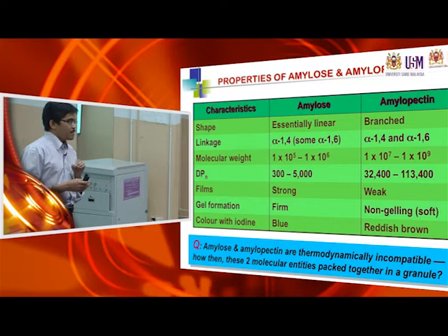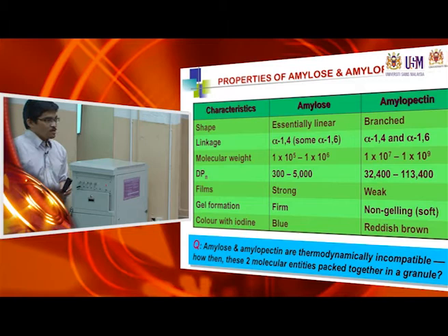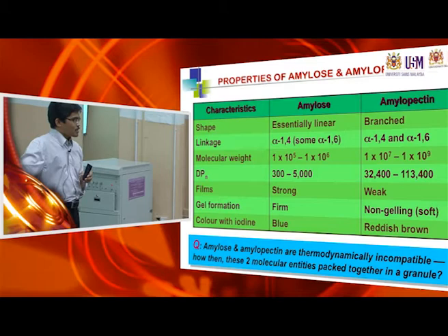What if we leave the starch solution without heating at room temperature — we just leave it for one hour, two hours, a few hours? Do you think the granule will swell? No heating, no temperature change, just ambient room temperature — leave it for ten hours. It will swell a little bit, around maybe 20 to 28 percent of its original volume, but just a little bit.